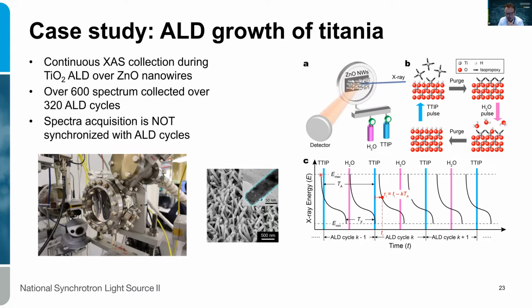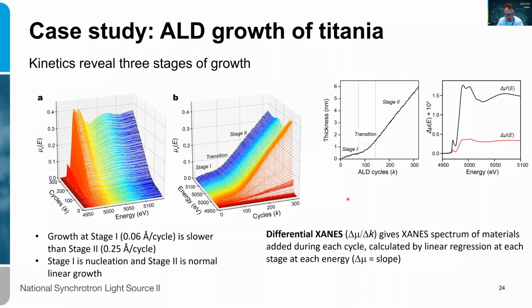And the way we are taking this data, the ALD happens on its own time scale, right? When the pulse needs to come, it comes. But then we have our own cycle of measurements, and I wanted to show you what kind of information we can extract from this. All right, so just from the kinetics of the growth, we can already recognize that there are three different steps. Stage 1, which is the nucleation on the surface, and stage 2, which is normal linear growth, and the transition period in between them. So that's good. That tells us something about the mechanism of the process already.